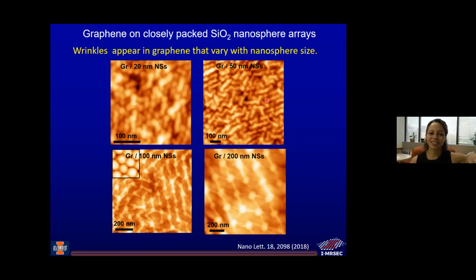You don't see any wrinkles. And then on 50 nanometer, it has more space. It's not pinned as strongly. So in between, it can release strain by wrinkling in these kind of bone patterns. Then on 100 nanometer graphene, you get more connected wrinkle patterns. And then on 200, you get these very clear lattice wrinkle patterns of graphene on top of the nanospheres.